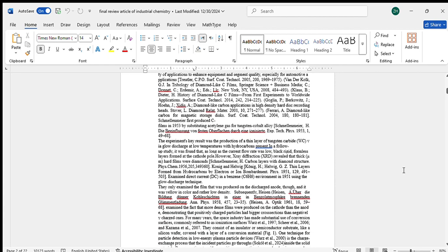In conclusion, DLC coatings are crucial for space missions that aim to detect low-energy neutral atoms. They provide a durable, efficient surface for converting neutral atoms into ions, which is necessary for gathering important data about space environments. These coatings are less than 50 nanometers thick with a surface roughness of less than 5 angstrom, providing a durable, efficient, and precise surface. The advancements in DLC coating technology discussed in the paper are important for future missions and will help us better understand the cosmos.